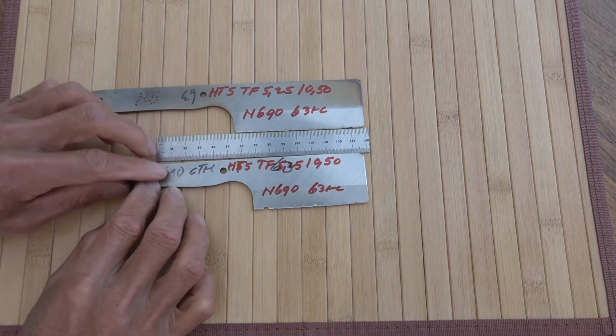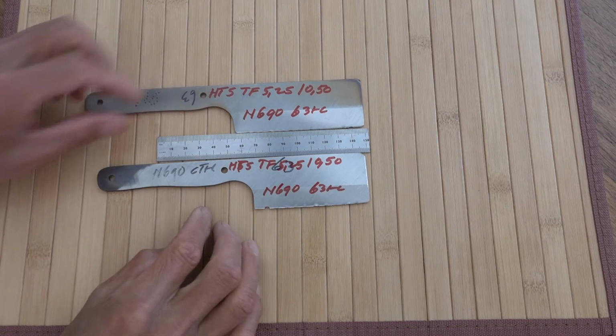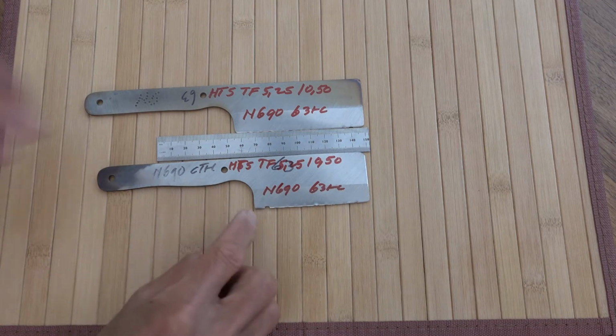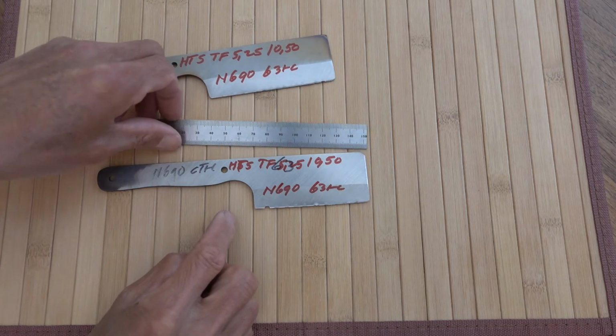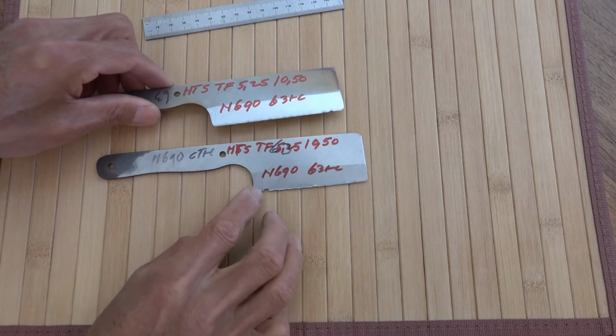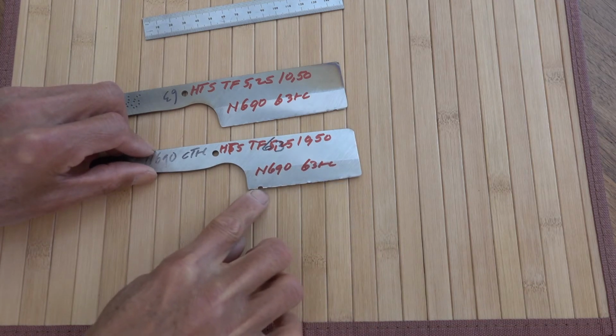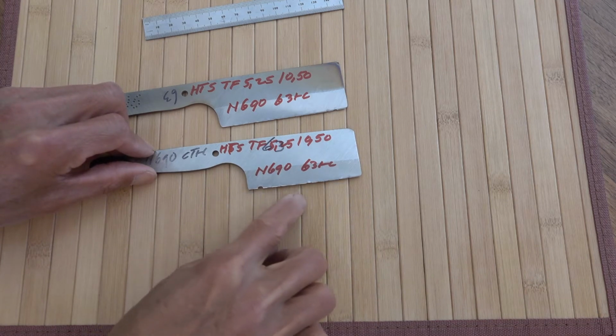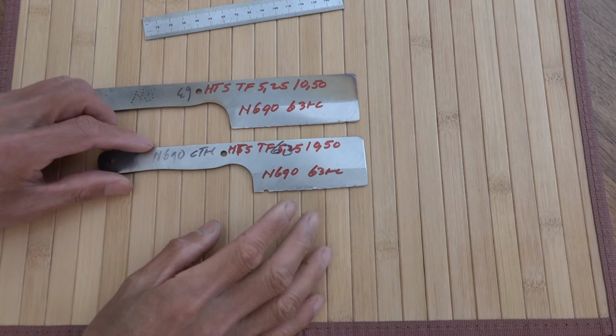And this is N690, and this is the control right here. N690 did better than AEB-L control here, except when it failed, they also ended up with big half moon, crescent moon chips here. So it's fairly good, actually, from just a standard heat treat instead of my 2 days.